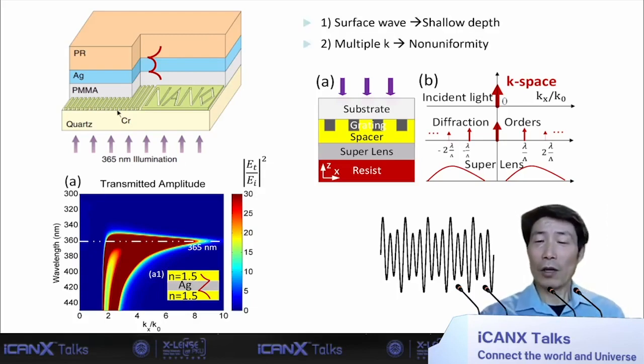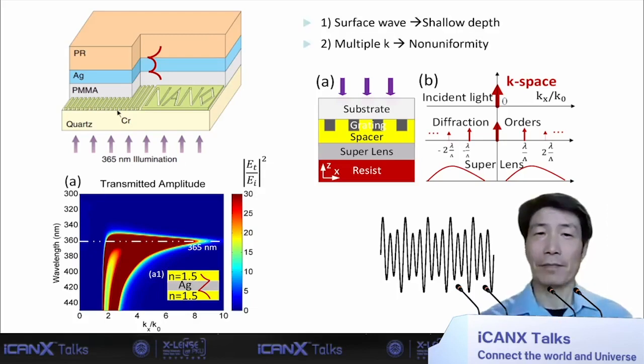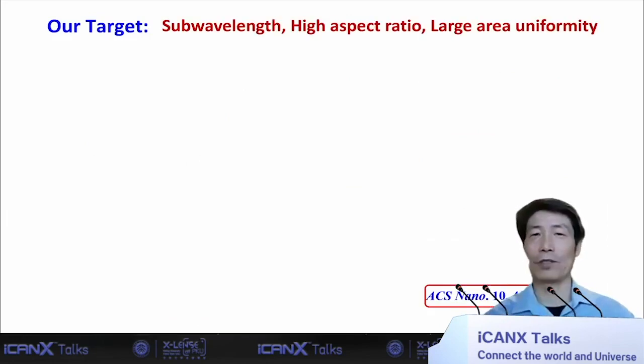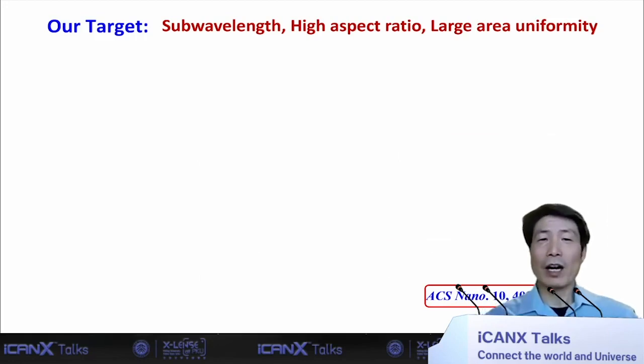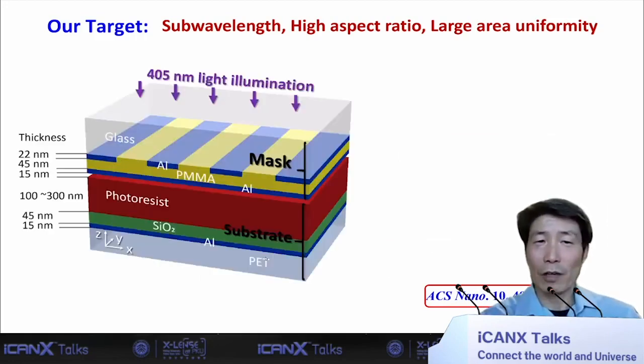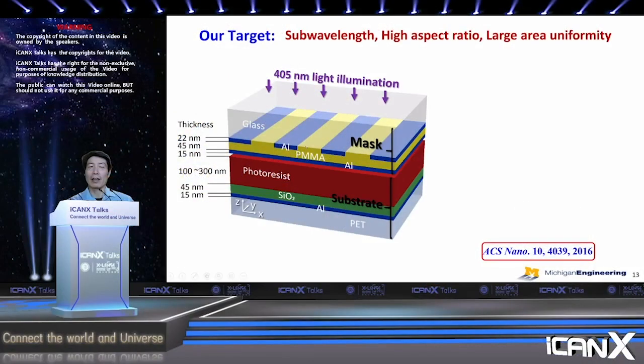So our goal is to try to address this. Okay. Our target is now, we want to still get very deep sub-wavelength, but we want to get a high aspect ratio so they are practical, can be useful. And we want to be able to pattern a large area with good uniformity. And again, it's as nano people, okay? The strategy we come up with is that we're gonna use a very thick layer of photoresist, okay? But that alone doesn't work because the wave is still evanescent when it's scattered off from a very narrow width grating mask, okay?